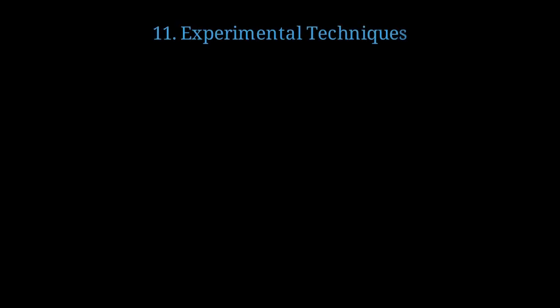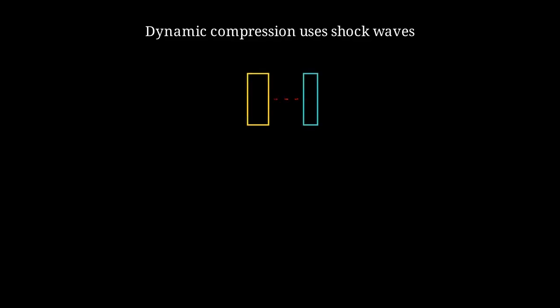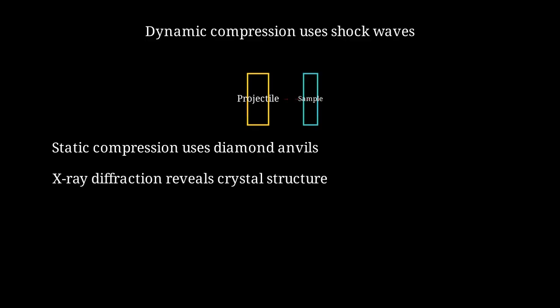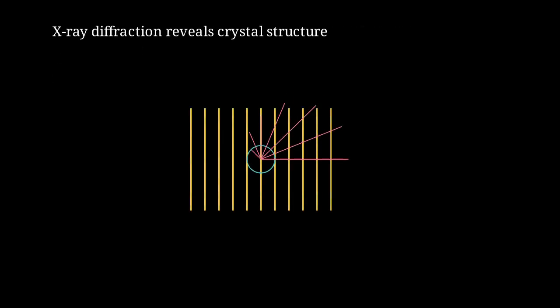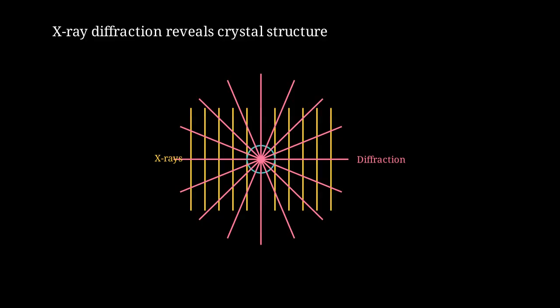Let's examine the clever experimental techniques scientists use to study these exotic phases. Dynamic compression uses powerful shock waves to compress water samples in microseconds, mimicking planetary collision processes. A projectile slams into a sample at high velocity, creating a shock wave that compresses the water to extreme pressures in microseconds. Static compression uses diamond anvils, which slowly squeeze samples while maintaining pressure for longer periods. Scientists then use X-ray diffraction to reveal the atomic scale crystal structure of the exotic ice phases. X-rays pass through the sample and diffract in patterns that reveal the arrangement of atoms, like a molecular fingerprint.